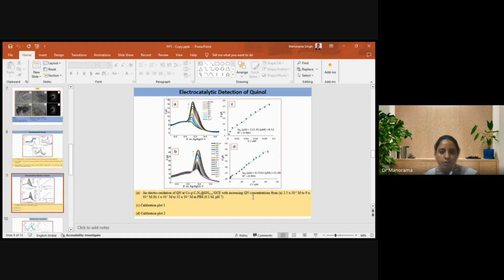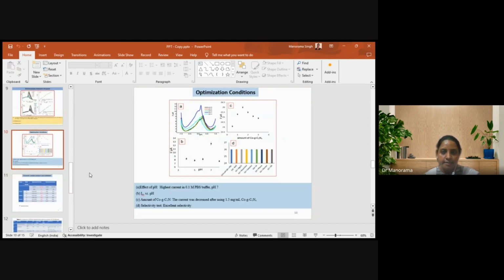So further, we have studied with the different concentrations of the quinol, and we found that yes, there is a good electro-oxidation response recorded with the differential pulse voltammetry, and we found two calibration curves. From 2.5 nanomolar to 9 into 10 to the power minus 8 molar and 1 into 10 to the power minus 7 molar to 32 micromolar in phosphate buffer saline. With this range, because the current increases linearly with concentration, that's why we have found two calibration plots, 1 and 2, with the different ranges, but in the series.